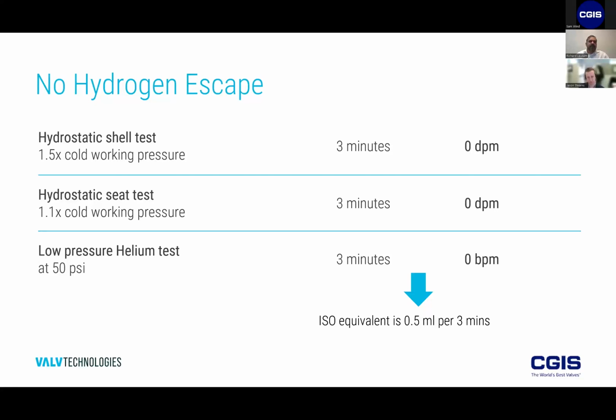So this is one way to test valves, and that is to have a hydrostatic shell test that's done at 150% of the cold working pressure, and the time is set to 3 minutes, which is greater than any of the standards. The acceptance criteria there would be zero drops per minute. The other way to do it is to do a seat test, so you're testing the integrity of how well the seat works. This can be done again at 110% of the cold working pressure. The time in which it's done could be higher than all of the standards, and the test criteria could be zero. And a low pressure helium test can be done.